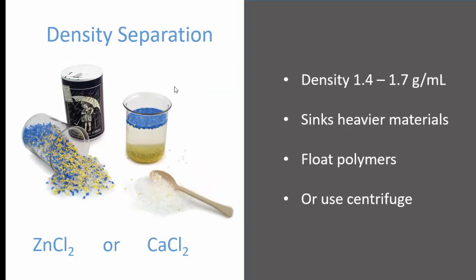The third key step was density separations. Throughout the literature, we'll see a lot of laboratories using either a zinc chloride or a calcium chloride solution at a concentration that makes it to a density of 1.4 to 1.7 grams per mil. In effect, the heavier inorganic type material sinks to the bottom, the plastic polymers float to the top, then those are skimmed off and analyzed.